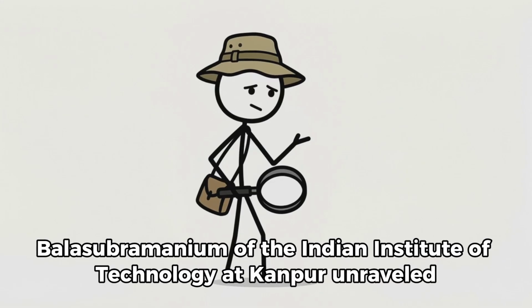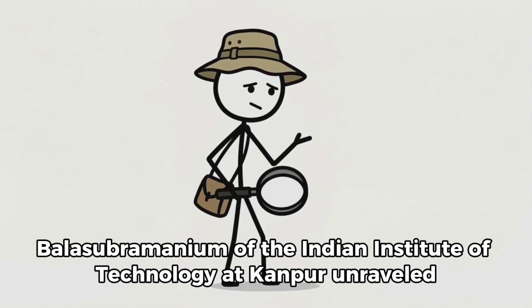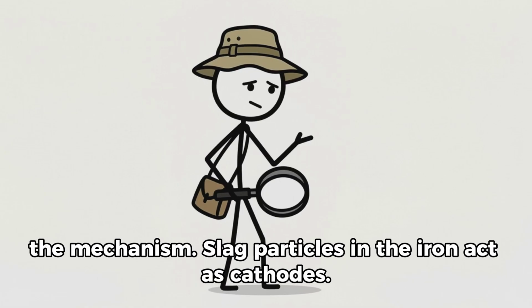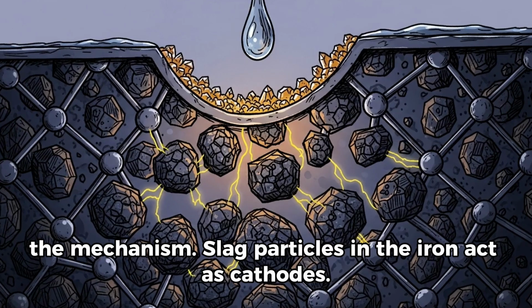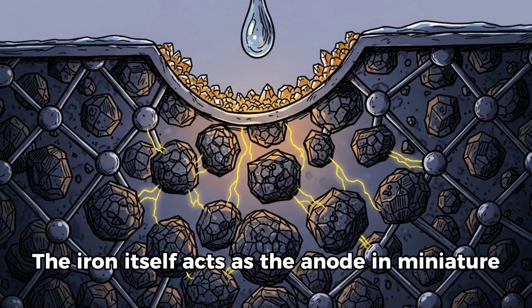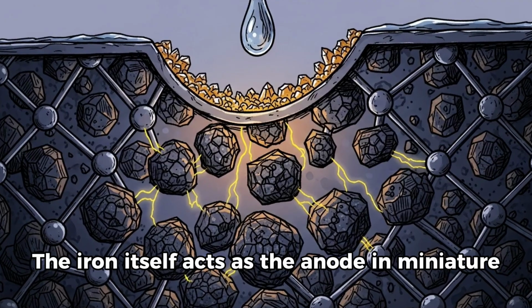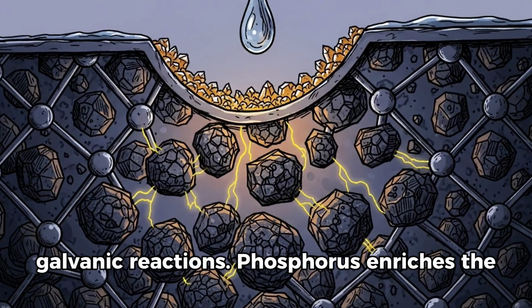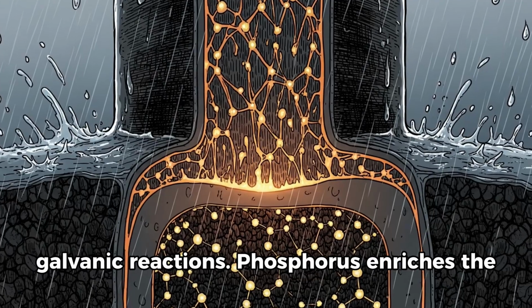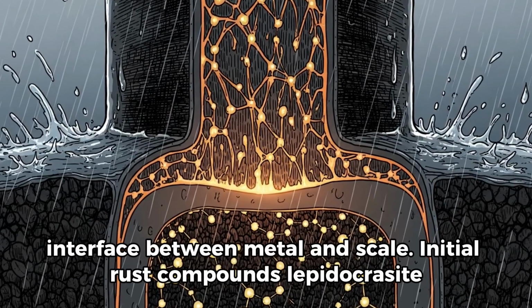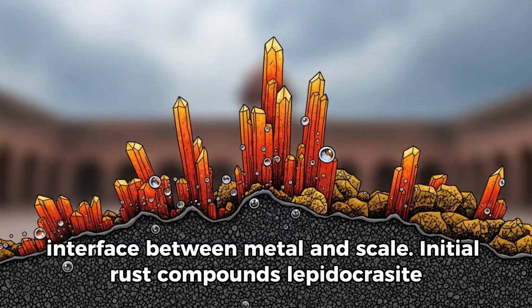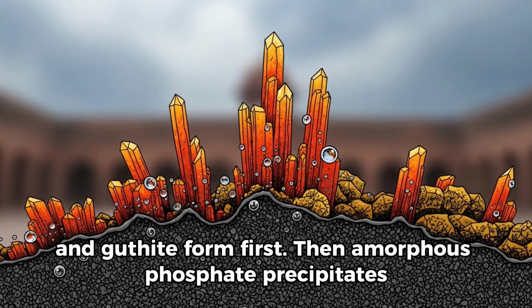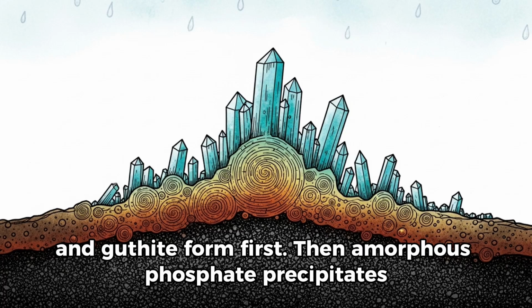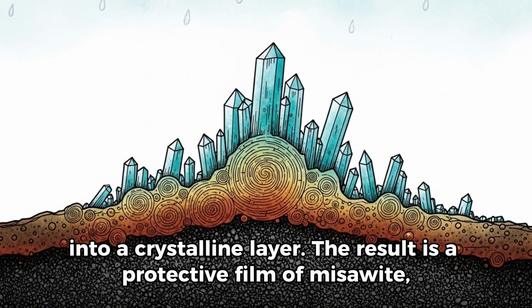R. Balasubramaniam of the Indian Institute of Technology at Kanpur unraveled the mechanism. Slag particles in the iron act as cathodes. The iron itself acts as the anode in miniature galvanic reactions. Phosphorus enriches the interface between metal and scale. Initial rust compounds, lepidocrocite and goethite, form first. Then, amorphous phosphate precipitates into a crystalline layer.